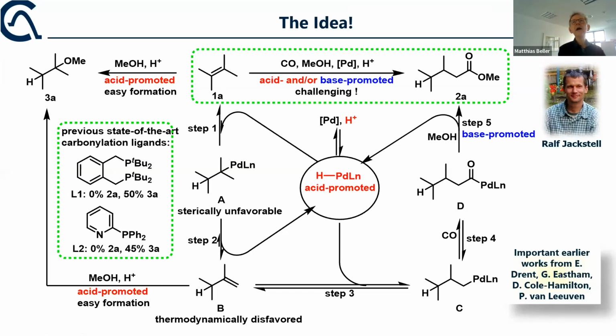And how can you approach this? What we did is we tested what we thought were the most active palladium hydride catalysts that we could imagine for this chemistry. So we used the Lucite ligand, we used the Drent ligand developed at Shell, we used many others, but they all were unsuccessful. They only gave the corresponding ether, which simply forms by an acid-catalyzed reaction, because as you know from basic organic chemistry, this forms a stable carbenium ion, and then this reacts very easily. So if we had not looked more carefully into the process, the story would be over now. No active catalyst. Then we tried to understand why the palladium hydride is not adding to the corresponding olefin.